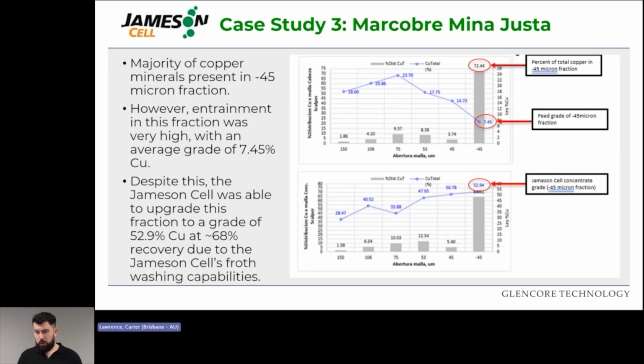Now, Marcobre were willing to share some size by recovery data for this, so a little bit more of a deep dive on this case study. Now, the majority of the copper minerals were present in the sub 45 micron fraction, quite common in cleaning duties. However, the entrainment in this fraction was very high, and so you can see there was an average grade at this fraction of 7.45% copper.